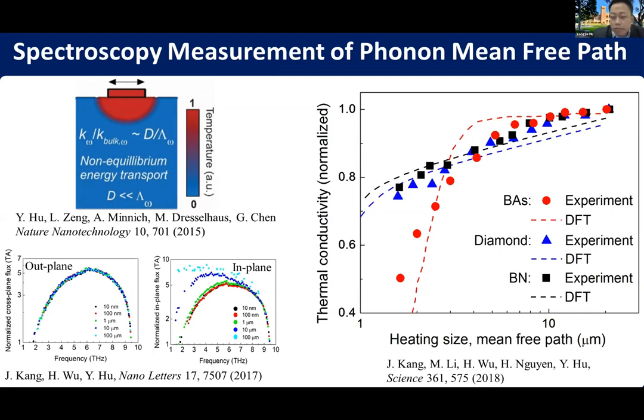However, in particular, boron arsenide has the largest reduction, up to 50% when the heating size is reduced to about 1 micrometer. So this indicates that in boron arsenide, a large portion of phonons have very long mean free paths over microns even at room temperature that contribute to about half of the total thermal conductivity. So this measurement verifies very long phonon mean free paths in boron arsenide due to its unique band structure, and also explains the origin of high thermal conductivity in boron arsenide.